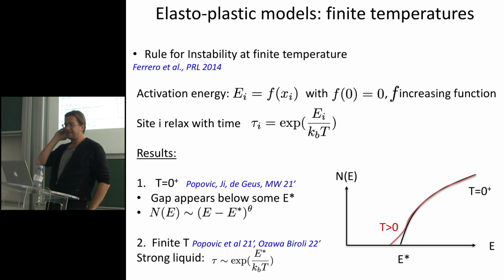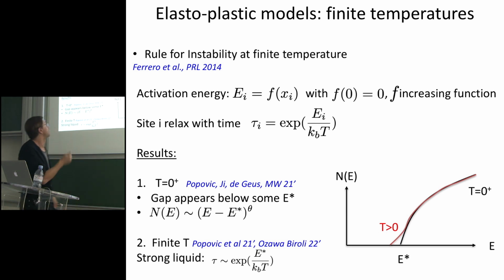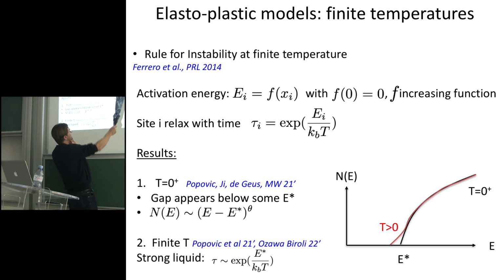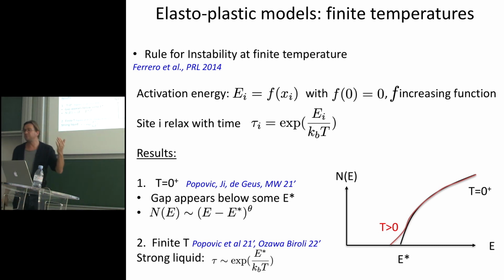Now, this system, you can also think about those kinds of models at finite temperatures. Essentially, you say that those blocks can also have a barrier, and they can relax above those barriers. And Ei is just the energy barrier of block i, which is just a function of the stability xi. If the stability goes to 0, then the energy should go to 0. And f should be an increasing function. If you have large stability, you have a larger barrier.